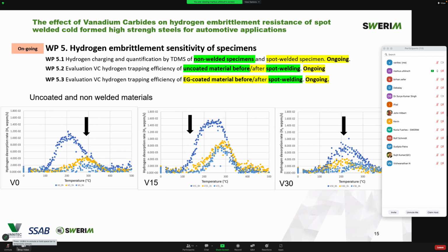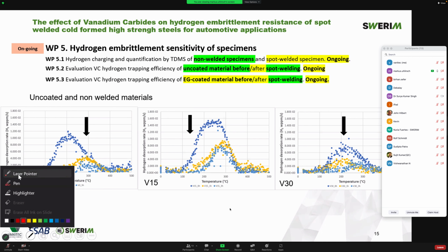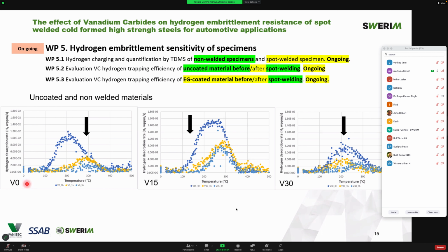So here we see the TDMS graphs of the materials with the different vanadium contents. Let me get the pointer. Here, the reference material without vanadium, 0.15%, 0.30%. For each of them, the hydrogen content was measured directly after charging. This is the dark blue curve for all of them, and we see it's the highest.